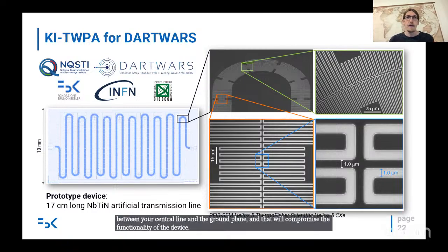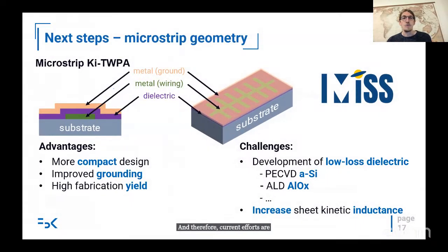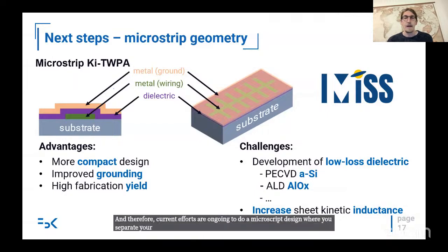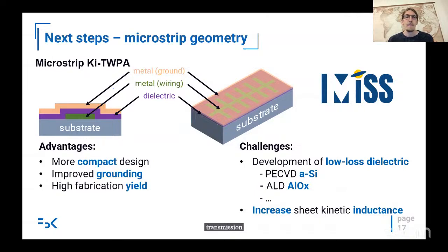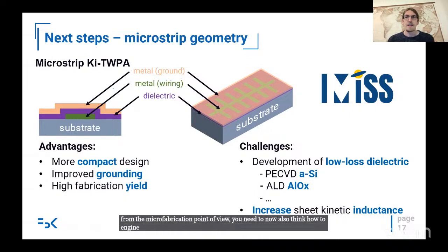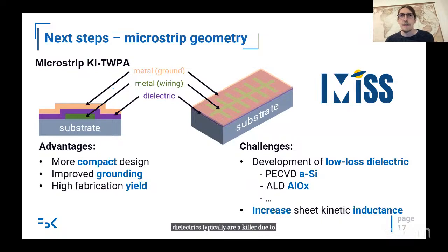And therefore, current efforts are ongoing to do a microstrip design where you separate your transmission line, the central conductor, from the ground plane by introducing a dielectric in between. So you no longer have a coplanar waveguide layout, but a microstrip layout. While this has many advantages from the microfabrication point of view, you now also need to think about how to engineer low-loss dielectrics that separate these two metal layers, which is a challenge, as in the microwave regime for qubits and for traveling wave amplifiers, dielectrics typically are a killer due to the two-level systems that are present in these materials.